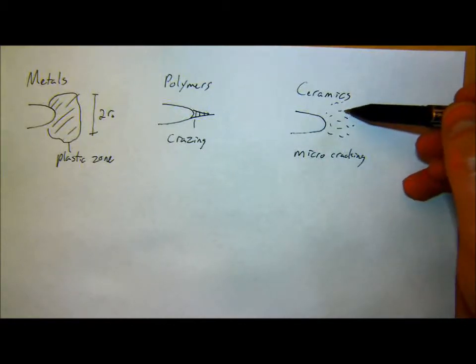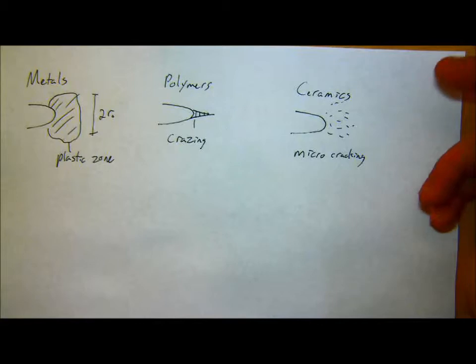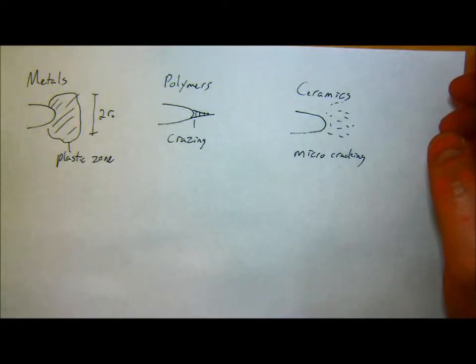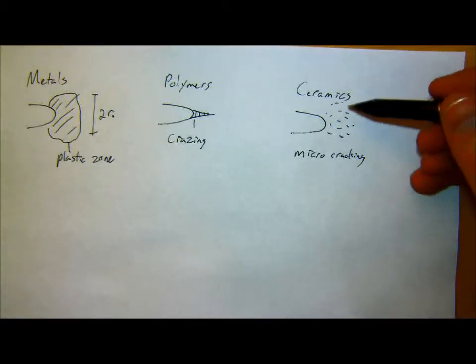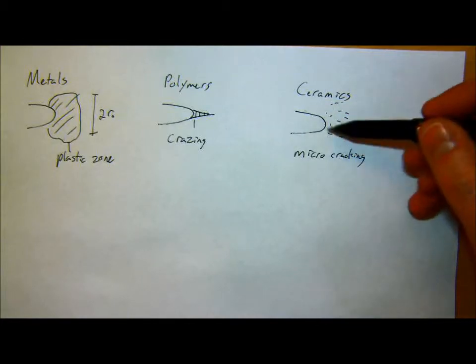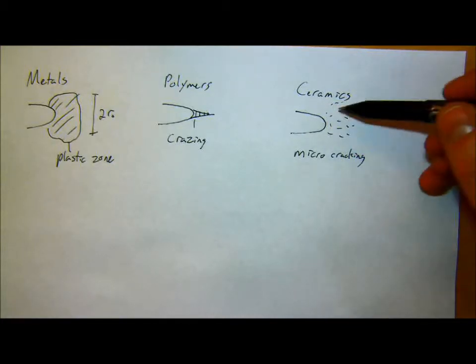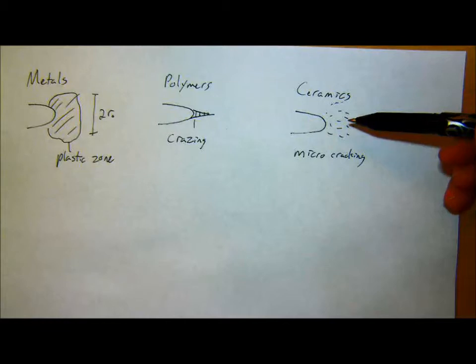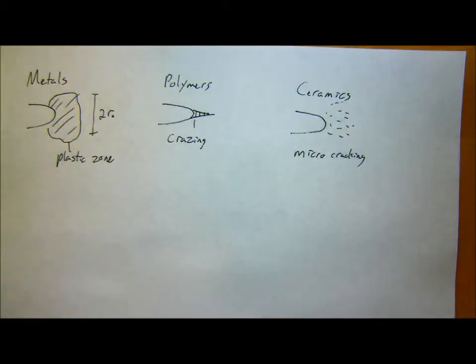But this process zone now is bigger or smaller for different materials, and I'll go through a little bit later on about how big those process zones are. But basically, the size of this needs to be small relative to our part size in order to have a valid Griffith criteria fracture test.